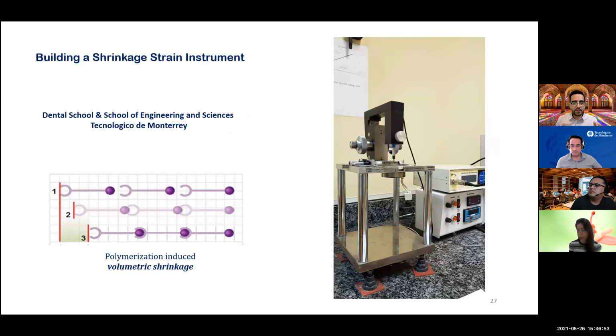So the last part of the research structure is the collaboration between the Dental School of Monterrey and the School of Engineering and Science of the Tecnológico de Monterrey, and we are going to build a shrinkage strain instrument for them, because when they are working in the dental school, they have some problems and they want to measure the shrinkage strain. I already mentioned it earlier in the presentation. If you have some monomers, first of all, they have only van der Waals interactions, and after polymerization, they have covalent interactions. The thing is that we get a reduction in volume known as volumetric shrinkage, and it's really nice if we can measure this.